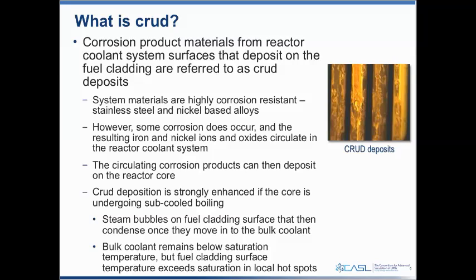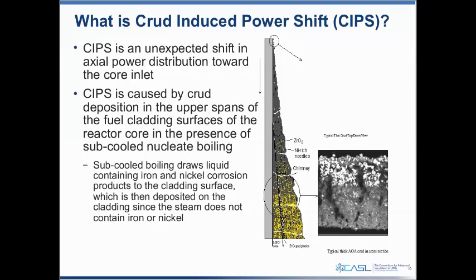So that's crud. One of the things we get concerned about is crud-induced power shift. Crud can cause unexpected things to occur, such as depositing neutron absorbers in the porous crud layer, which can result in an unexpected shift in power distribution. What we refer to as crud-induced power shift is really an unexpected shift in axial power distribution, typically toward the bottom of the core or toward the core inlet.